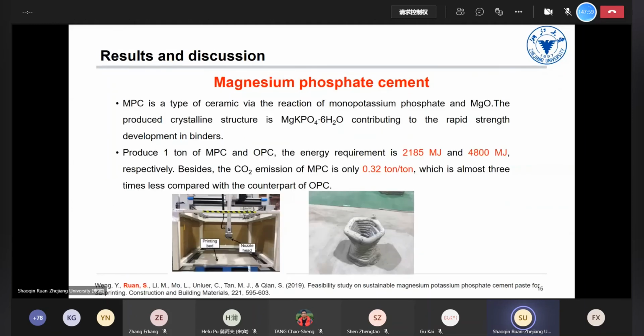That is the magnesium phosphate cement. Actually, we conducted several studies about its feasibility in 3D printing, and found it's quite effective because it is rapid setting. MPC is also a type of ceramic formed via the reaction of monopotassium phosphate and MgO, and the produced crystal structure is struvite, contributing to the rapid strength development in binders.